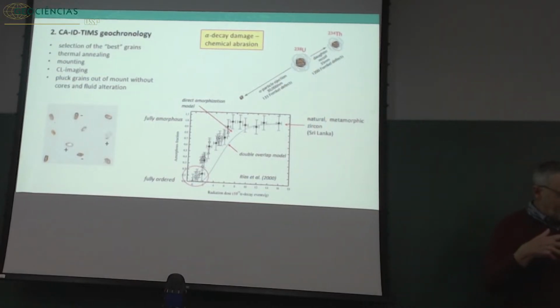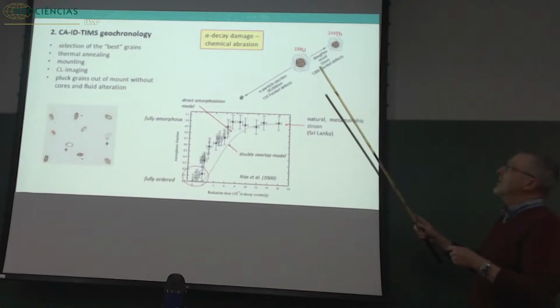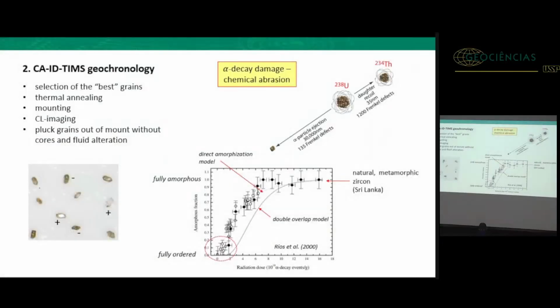So every alpha decay from the first uranium parent to the last stable radiogenic daughter will produce a damage in the lattice. So the 238 uranium is decaying via alpha, this is the alpha particle, and the first daughter is 234 thorium, which will travel a bit away, so it's not anymore on the stoichiometric site, it's an interstitial site, and this transfer here, even if it's only 35 nanometers, will create a lot of damage. So Frenkel defects are just damages.